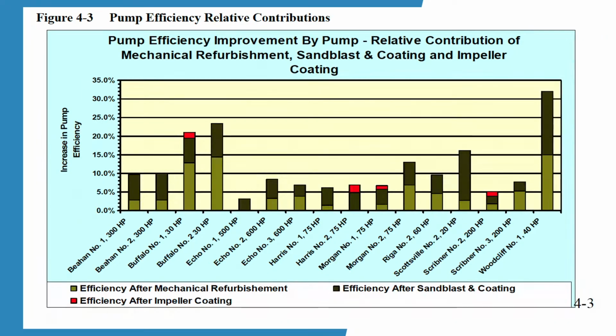Here's on the impeller. It's a little bit hard to see in the slide, but you can see the efficiency after mechanical refurbishment. That's going to be the dark right here after the sandblast and coat. And you can see the red, that's right here. So on this 30 horse, we did see a little bit of efficiency increase. Same thing on the 75 and the 75 here and the 200 horse. So it's only 4 out of, I believe, the 17 pumps that they ran this test on when they were coating the impeller.